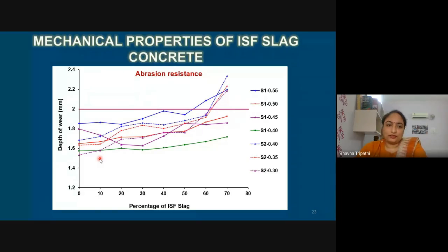And if a concrete specimen is having abrasion or wear less than 3.5 mm, then it can be used for general purpose tile, or in factories also it can be used. In that sense, all of the concrete specimens can be used for general purpose tile, and particularly up to 50% replacement, all the concrete mixes which have ISF slag up to 50%, we can use the concrete for preparing heavy duty floors also. Now, interestingly, what I want you to see is the control mixes. All of the control mixes have the average wear of less than 2 mm. So there was no problem in the concrete. The concrete was very much supporting the required abrasion resistance.